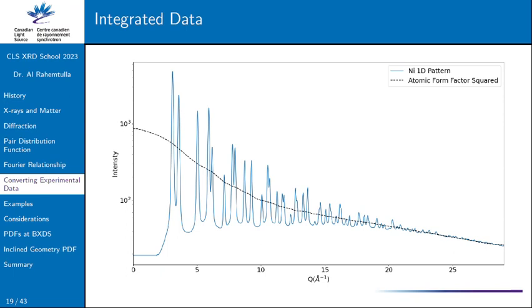So if you're coming in at a really low angle and out, it's almost completely constructive, whereas if you come in at high angles, then it becomes almost completely destructive. And so the scattering from the collection of electrons that makes up an atom is very dependent on the angle for how much of it is destructive interference from within an atom. That's one of the reasons why X-ray diffraction patterns fall off at high angles, because of the individual atom contribution. So the form factor is just showing how much an individual atom scatters at a particular angle.